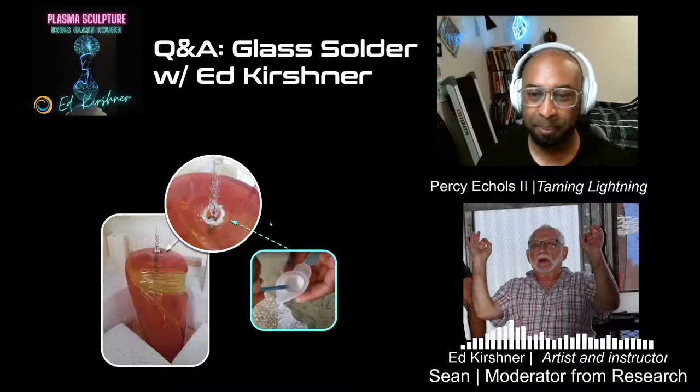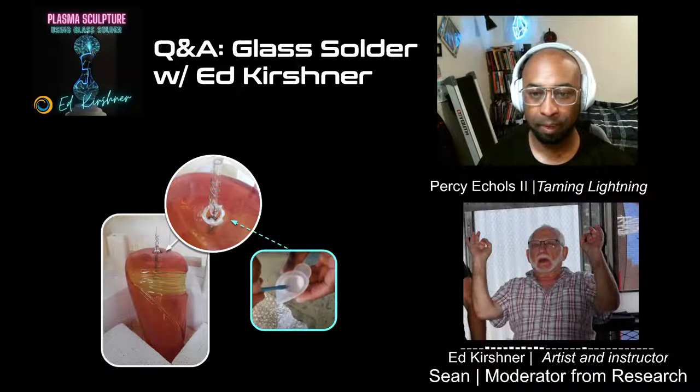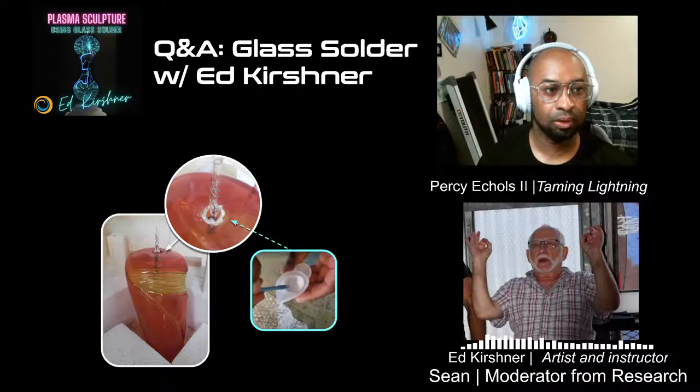So this is just illustrating adding in the solder here. You'll find, and by the way, this is something I haven't talked about much, different kilns do the solder differently, for a reason I do not understand. So you're getting a very white solder, right? Most often it'll be more gray, and sometimes a little, depending. And if you're really lucky and it's thin, it'll be sort of clear, translucent. But in some kilns it must reduce, because it comes out black. And sometimes you have to check your kiln.